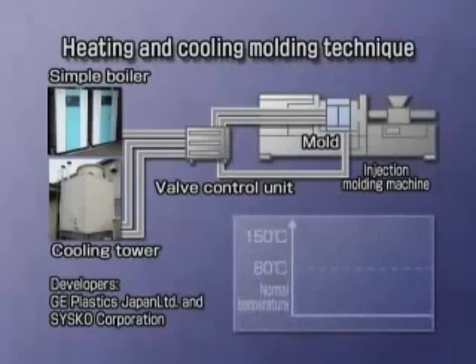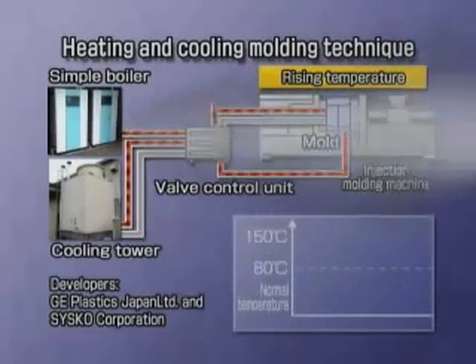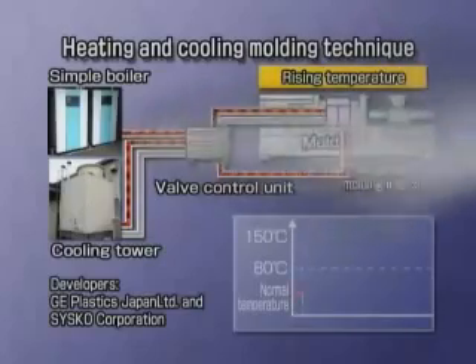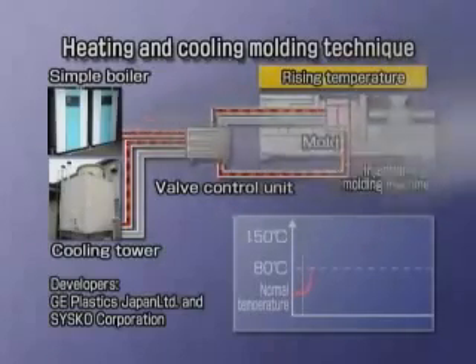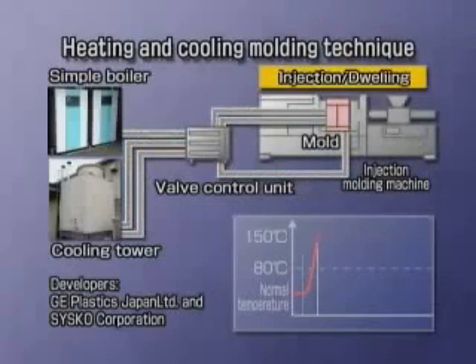First, the mold is preheated to a temperature higher than the thermal deformation temperature of the resin to be molded before injection. Then, the molten resin is injected, thereby achieving good surface quality, having no weld lines.